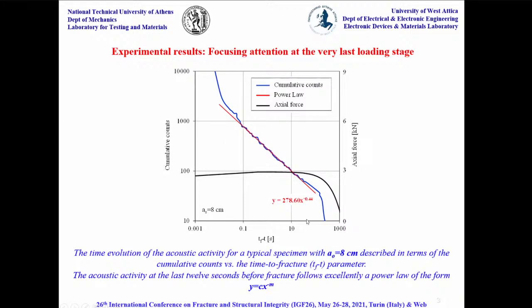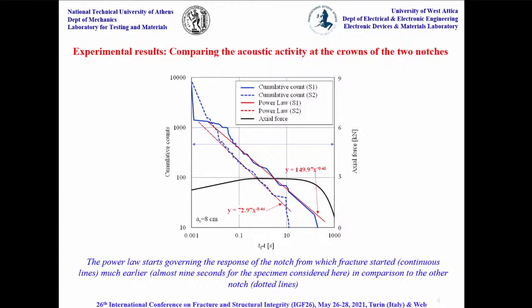You can see here that the acoustic activity, if described in terms of cumulative counts, seems to obey very satisfactorily a power law, which is already concluded when we describe this acoustic activity in terms of their function, as will be seen later. It was very systematically observed for all classes of specimens with very little scattering. And what is more interesting, this power law starts governing the behavior of the notch from which fracture starts much earlier in comparison to the notch which did not cause fracture propagation from the tip of the notch.